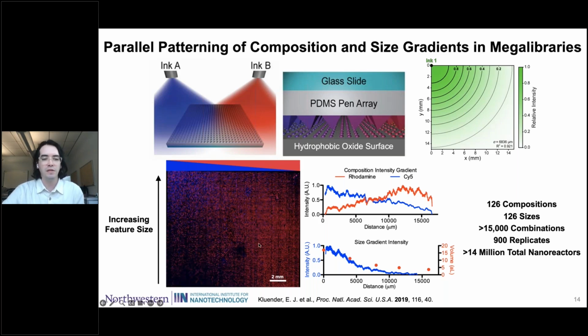And so you can see on this bottom left image, it's a pattern of nanoreactors containing red and blue dyes. And so you can see the color change for composition control. You can see the intensity change is the size control in the nanoreactors. And so in this example, we have over 120 compositions and sizes each. So it's over 15,000 combinations that we're making in parallel. Each one has 900 replicates, and so over 14 million total reactors. So it's a big increase in scale relative to the serial composition gradients, as with the perovskites, where that was just around 4,000 unique compositions.